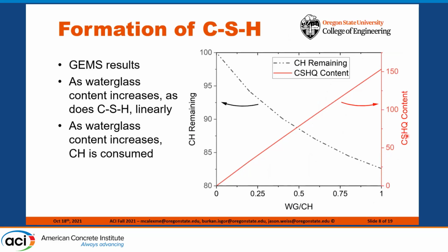will not go into further details about here, but as can be seen on this plot, as the water glass to calcium hydroxide ratio increases, the CSH content does as well in a very linear-like fashion. CH consumption also increases as well. Since the CH remaining decreases, that means the consumption is increasing.